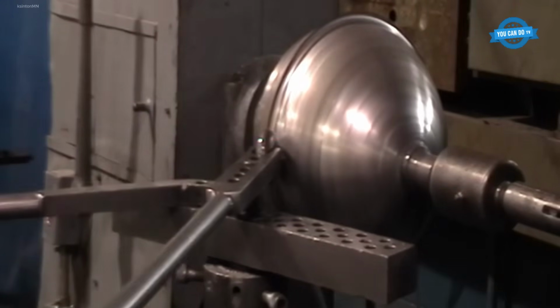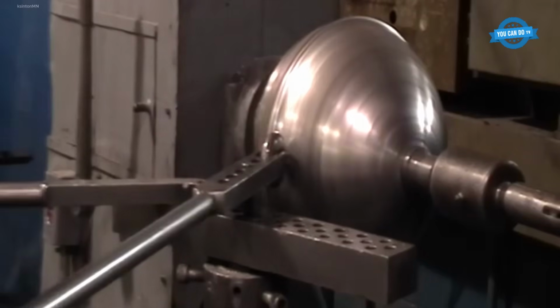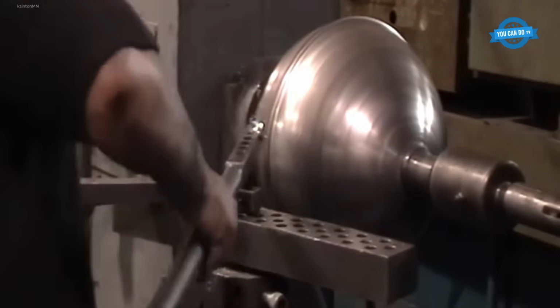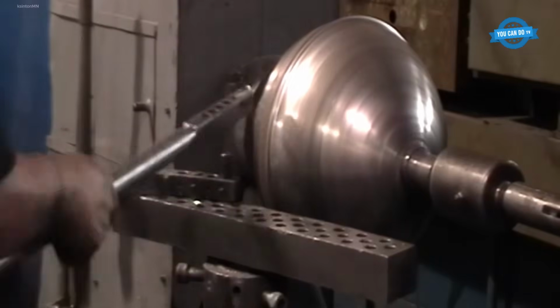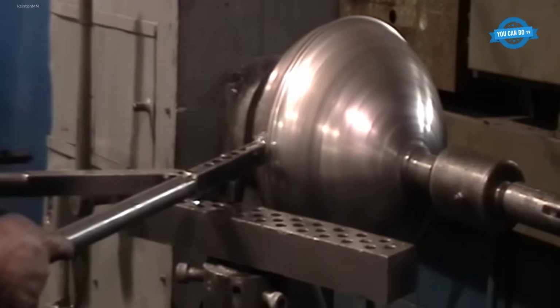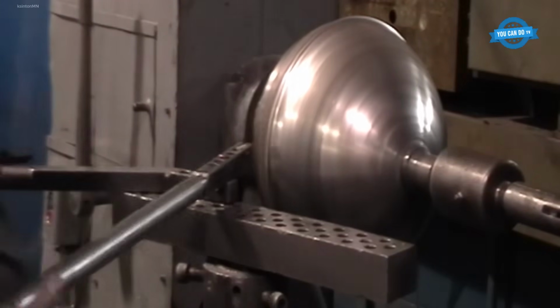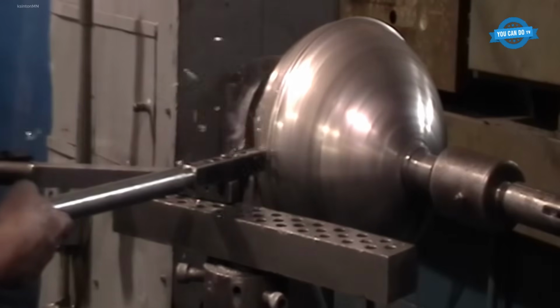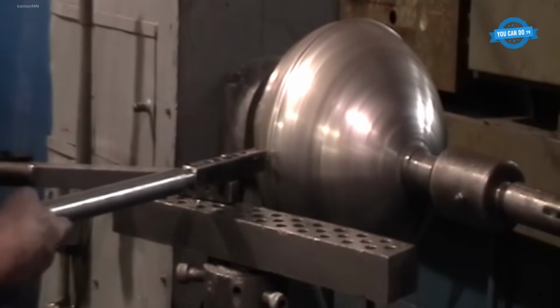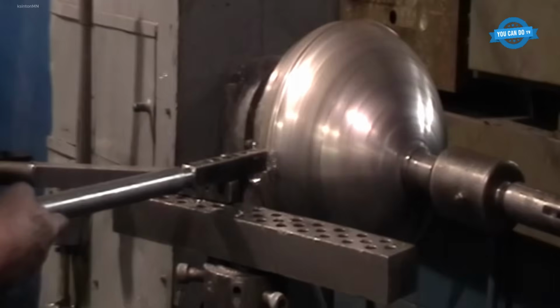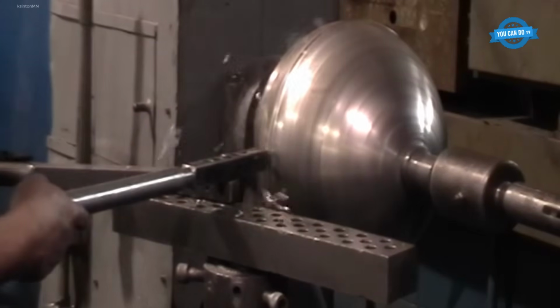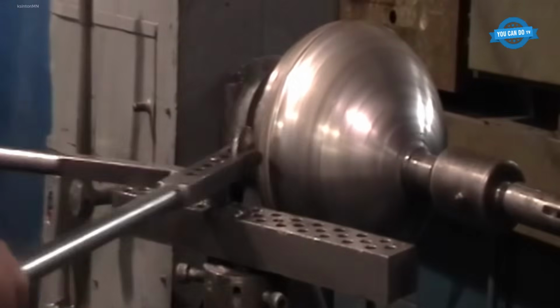The process continues with successive passes of the roller, refining the curvature and thinning the metal as needed to achieve uniform wall thickness. Critical parameters such as rotational speed, tool pressure, and feed rate must be precisely controlled to prevent wrinkling or tearing. The metal's ductility allows it to conform without cracking, while internal stresses are minimized through even deformation.